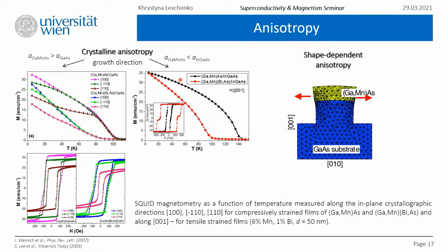And this is confirmed by the superconducting quantum interference device measurements of the magnetization as a function of the applied magnetic field at low temperatures. So for the simplest growth on gallium arsenide, the easiest magnetization direction will correspond to a hysteresis with a more square-like shape and a higher magnitude. And it is the case for 100 for both ternary and quaternary compounds.